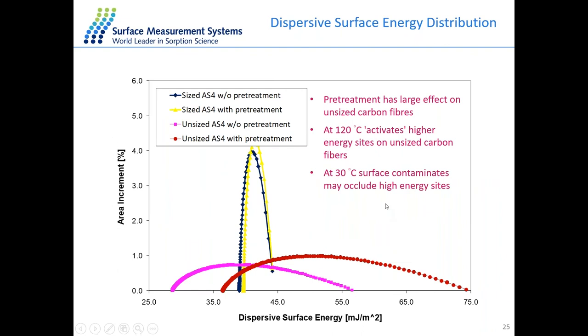And in case of the conditioning temperature, here is the higher temperature, which is the red line for 120 degrees, compared to the pink line here for 30 degrees. The higher temperature will activate the surface and remove all the contaminants on the surface. That results in a higher surface energy compared to the lower temperature, the pink one here. And in case of the sized carbon fiber, the two temperature plots are almost the same as each other, just overlapping on the plot here.